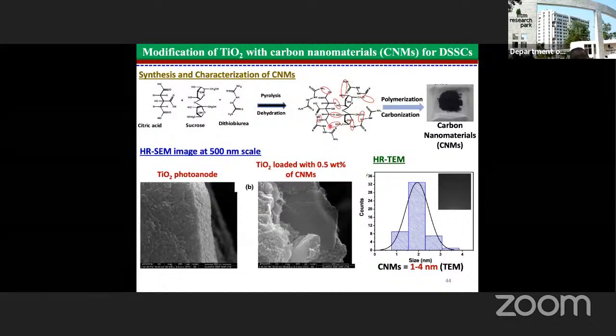The problem with pyrolysis is you don't know what is happening or forming, some black thing forms. But she put her mind to it. She took this material, did some dialysis, and selected carbon nano materials of a particular size, I think 1 to 4 nanometers, very selective. You get a big carbon mass, but she selectively removed only the carbon nano dots of this size, which she incorporated into the TiO2 layer.